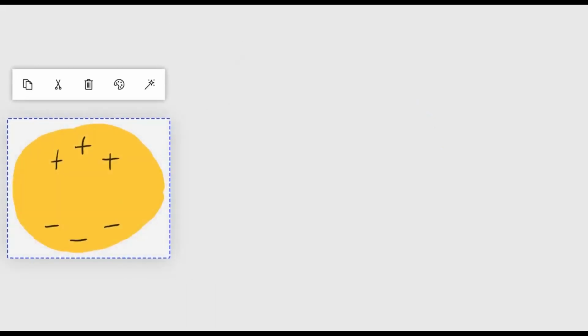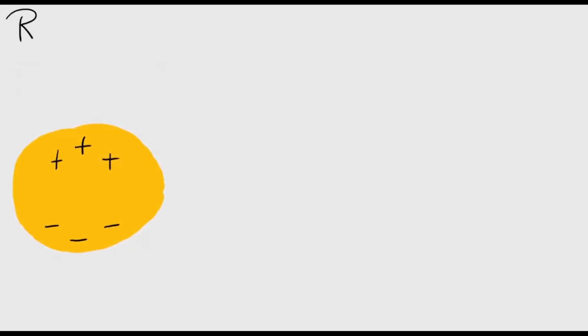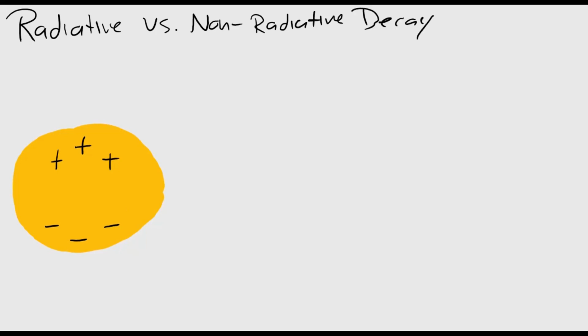resonance. After excitation, the plasmon relaxes through two channels: radiative decay, or scattering, and non-radiative decay, or absorption. Extinction refers to the sum of these two processes and represents the total amount of incident light removed by the nanoparticle. The balance between these two processes can be modified by altering the metal nanoparticle's shape, environment, or composition, and can be optimized to favor one property over another, and thus one application over another.